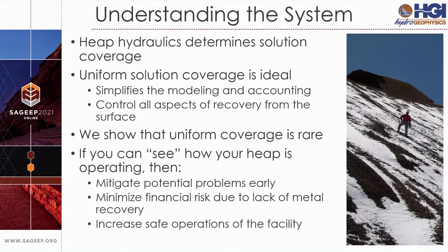I have mentioned that the heap leach pad can be viewed as a porous media that is irrigated from the surface. This is much like an irrigated field in agricultural settings. The media in the heap is to remain undersaturated for both stability and optimum extraction from a metallurgical standpoint. Therefore, we would expect that the hydraulic parameters that govern unsaturated flow will control the wet up of ore and extraction of metal, with the goals to have as much ore wetted as possible, and for that wetted solution to